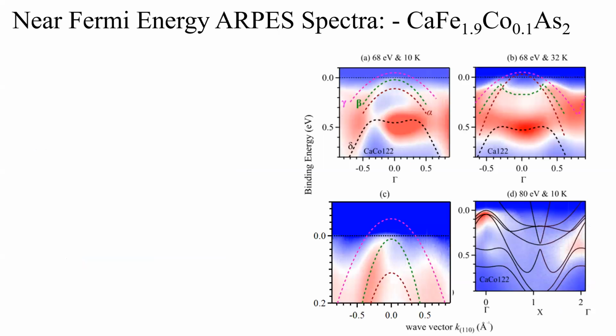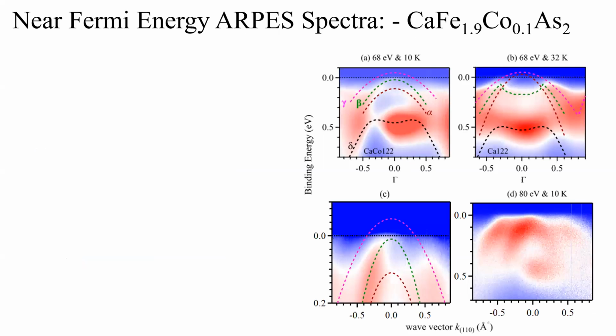So then we looked at the electron structure of the cobalt doped compounds. Of course, it would be difficult to say from here. So here, this one is basically the zoom of this part. This one is also the same thing, but taken at a different photon energy value. We see a nice band which is going like this, and there is another band which is going like this, and close to here there is another band. So what we are basically seeing is that while in the parent compound, both the alpha and the gamma bands were crossing the Fermi energy.